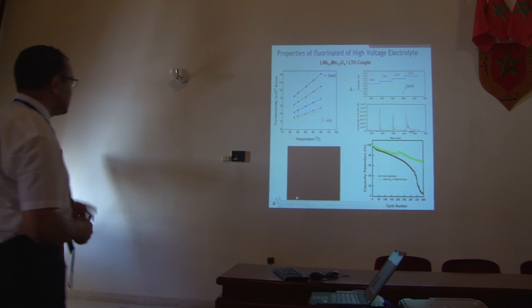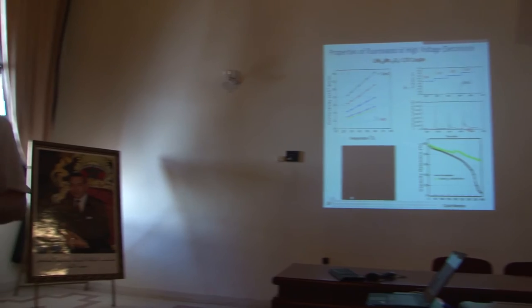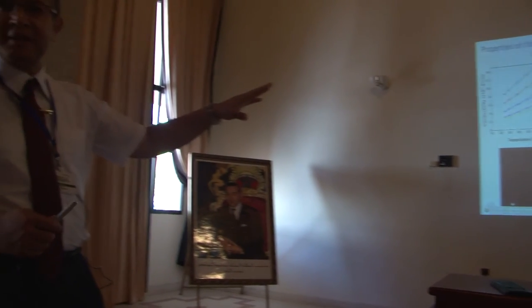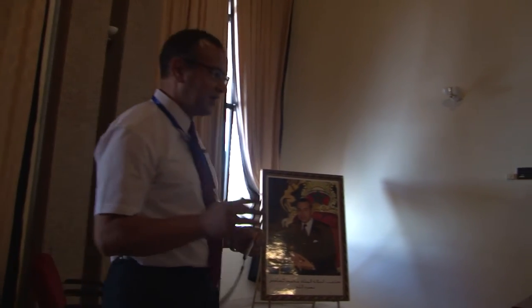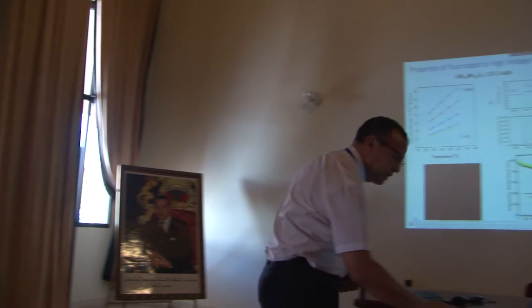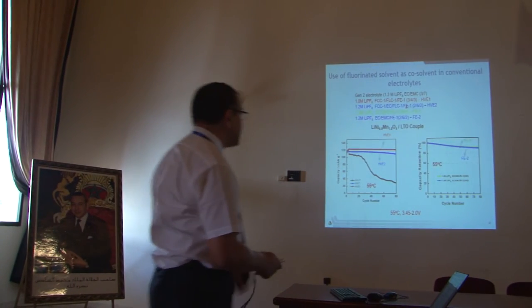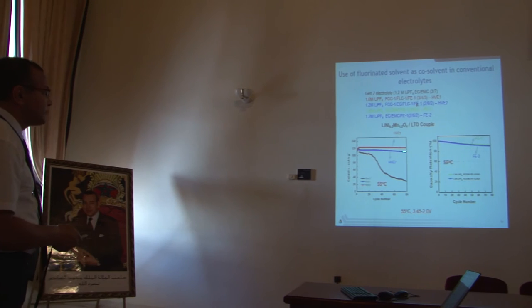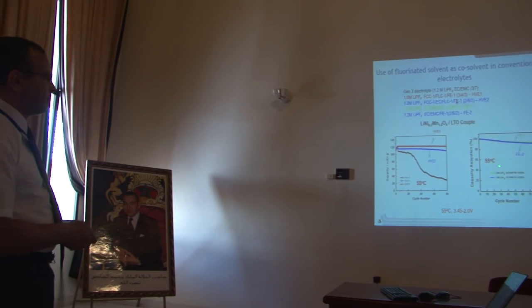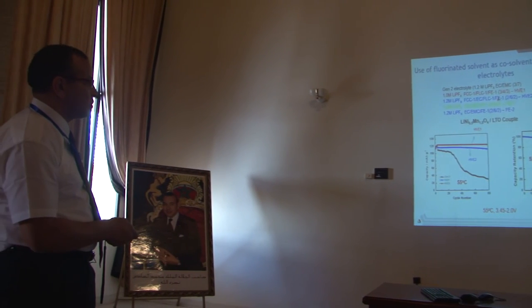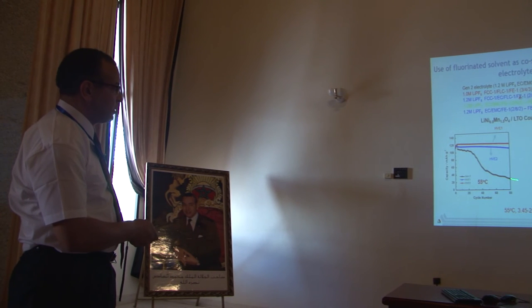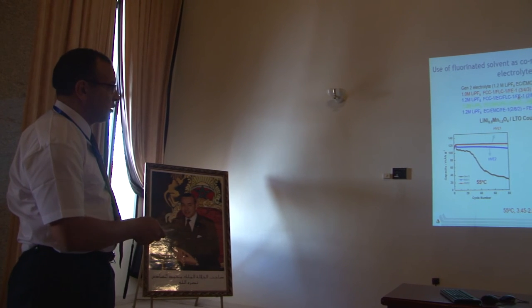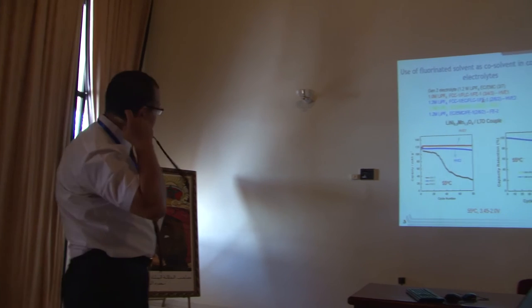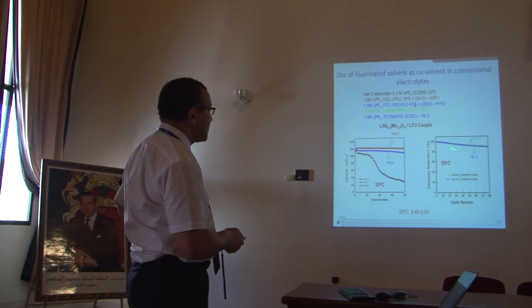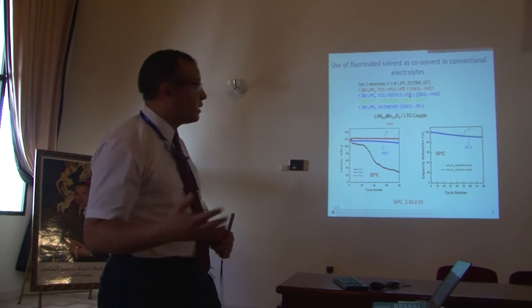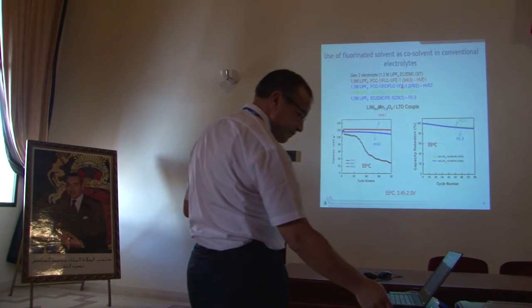So here is basically a flame test that shows that this type of electrolyte is non-flammable. We did also look at partially fluorinated, and they also work very well. You see both at room temperature and high temperature, the non-fluorinated one's capacity drops very quickly. The partially fluorinated also shows very good promise. In this case, you can use them with high power because they do have high conductivity.